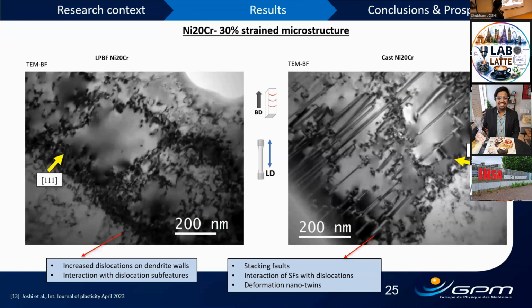When comparing with the cast microstructure, we see a completely different picture, a completely different story. We see stacking faults interacting with some dislocations, and also nano twins or twins in other micrographs. This is not very clear here. And in the extensive microscopy that we did on nickel 20, the LPBF samples, we do not see any twins in LPBF.